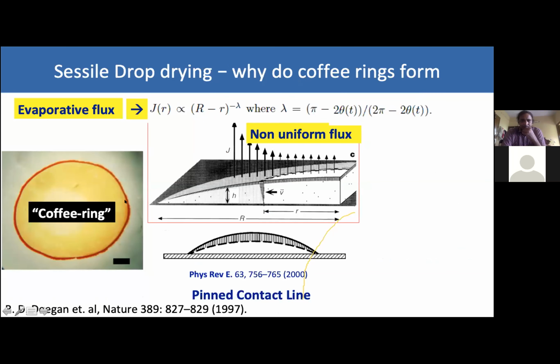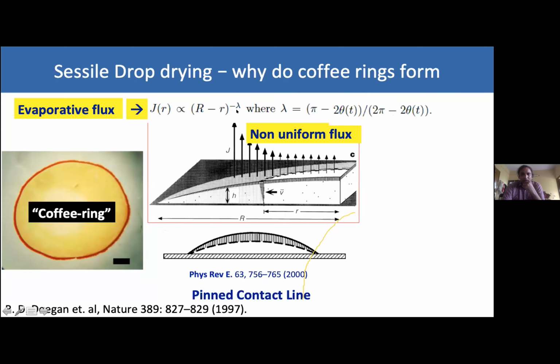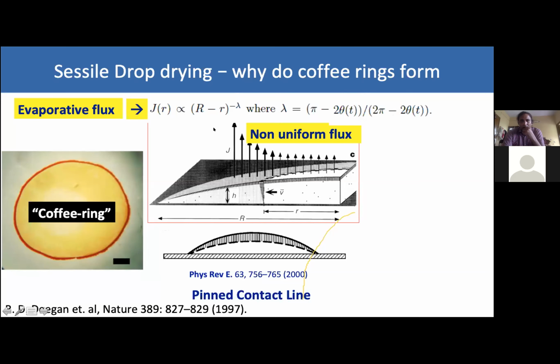Now, the reason for the formation of these coffee ring deposits has been attributed to what is called a non-uniform evaporative flux. One could derive an expression for the evaporative flux occurring from the droplet surface, and it turns out that it goes as 1 over (R minus r) to the power of lambda, where lambda depends on the instantaneous contact angle of the fluid drop, and R is the radius of the drop, and small r is any radial location from the center. If you take a typical example of lambda equal to 1, J of r is proportional to 1 over (R minus r).